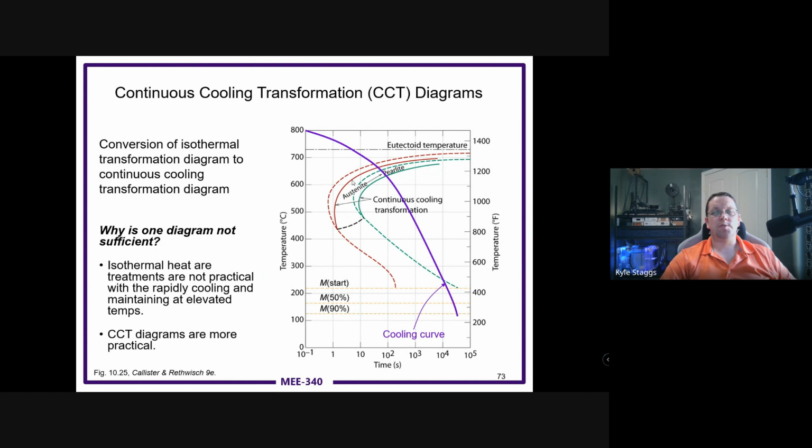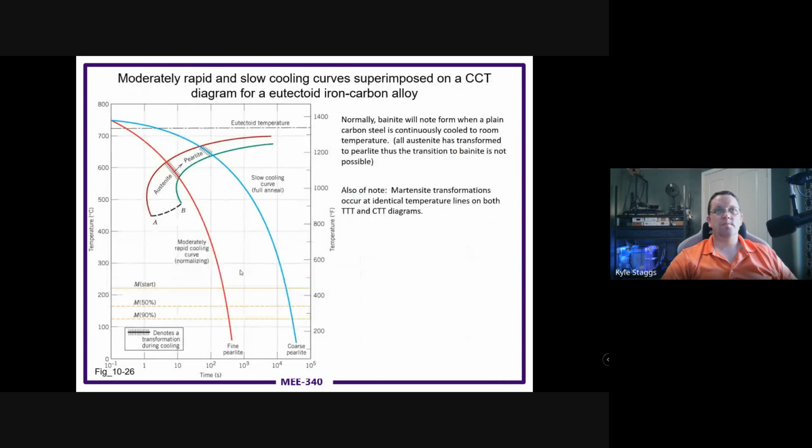The reason being, because this is a log scale, the farther up you are, the longer you're taking in the pearlite region, so you have a tendency to grow large grains. Down here, you're spending a lot less time, and that gives you a bunch of small grains because they don't have time to grow together and continue. This is really what it looks like. Your transformation time is very short here, so they don't have time to grow the much longer grains of pearlite in the same way.